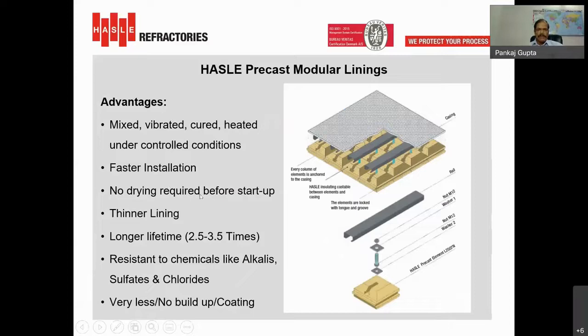No drying is required before the startup. Thinner lining is possible. Longer life can be expected compared to castable lining. These are resistant to chemical attacks from alkalis, sulfates and chlorides, and hence provide very little buildup or coating.